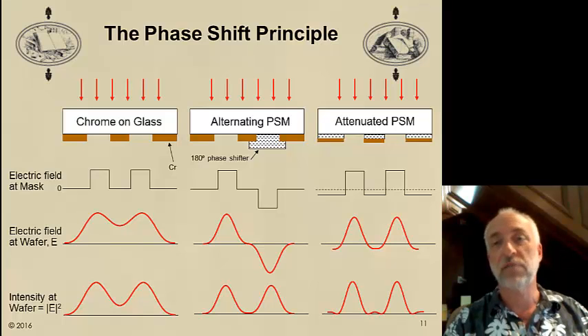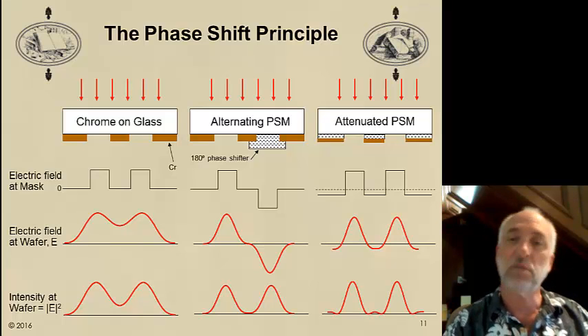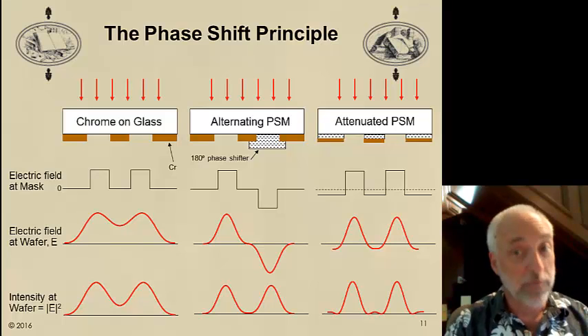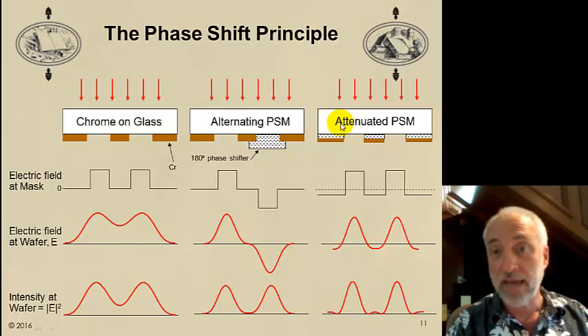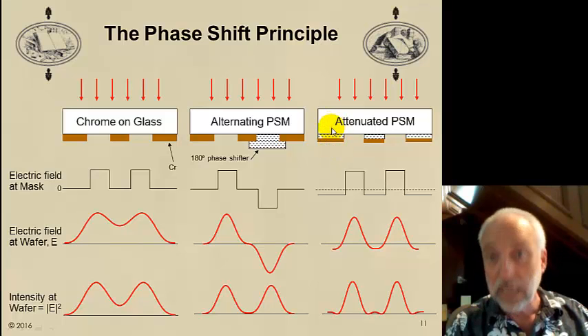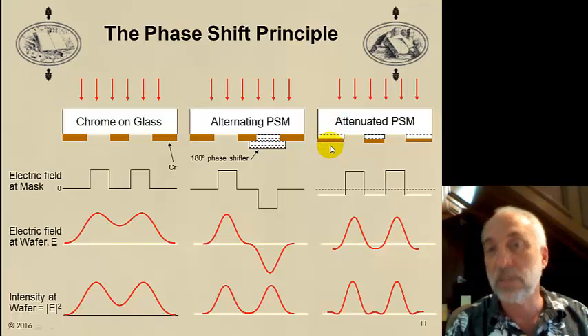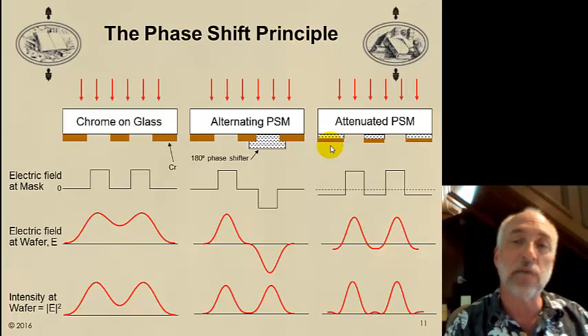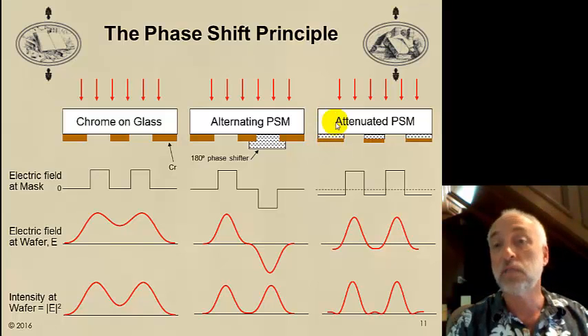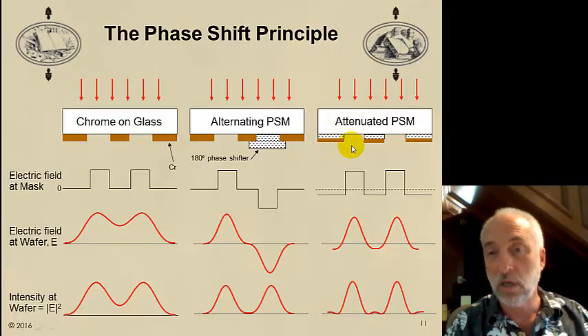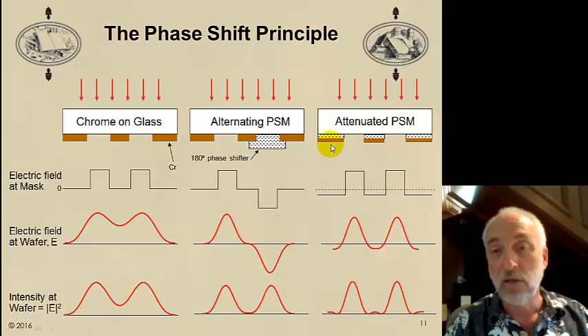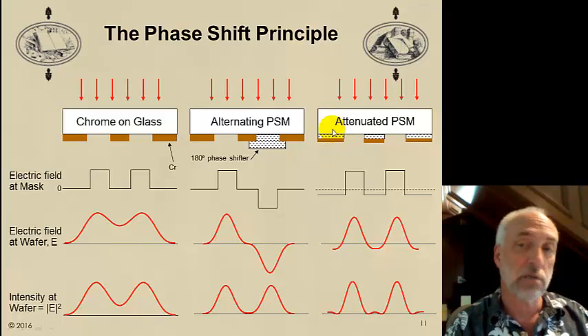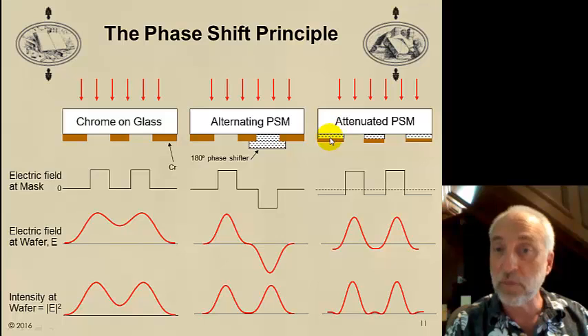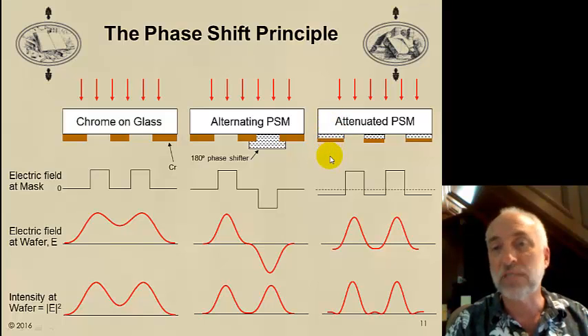Another style of phase shifting mask is the attenuated phase shifting mask, where we have this molybdenum silicide material that is not 100% opaque. It allows a small amount of light to be transmitted, say 6% of the intensity or 9% or 12% of the intensity is being transmitted compared to 100% that's going through the space. Now, at first you might think that's bad because our features are not as dark as they should be, but I not only adjust the transmittance through this material, but I'm also changing the phase of the light, making it 180 degrees out of phase.